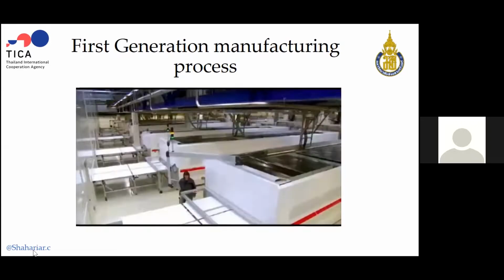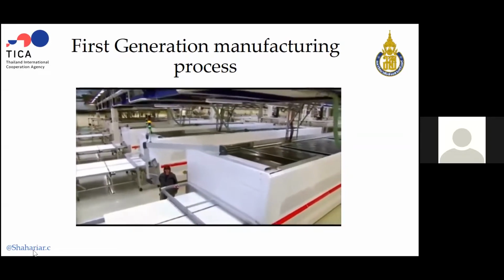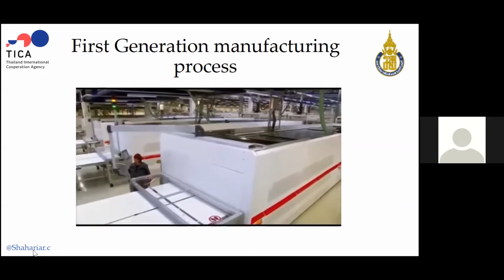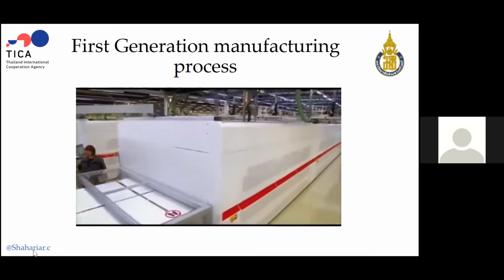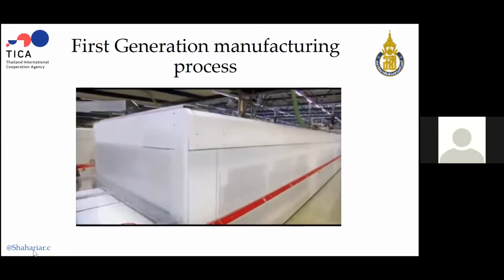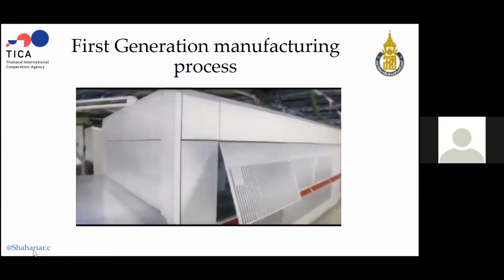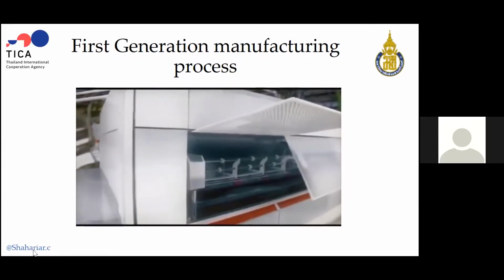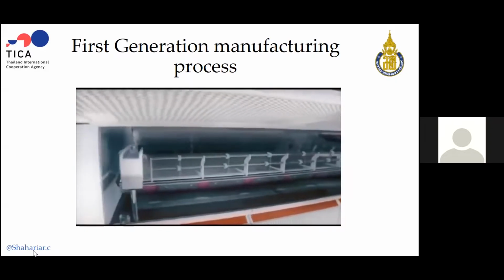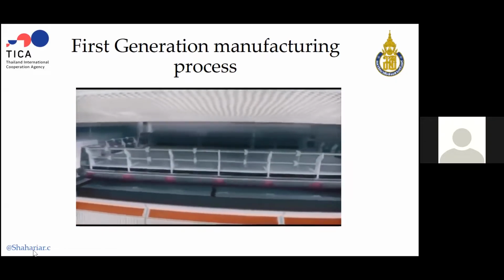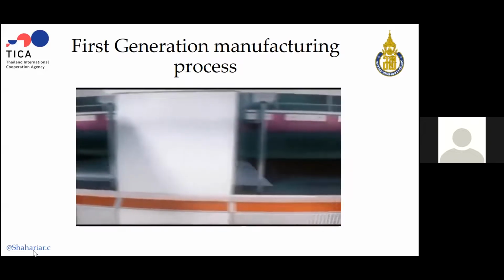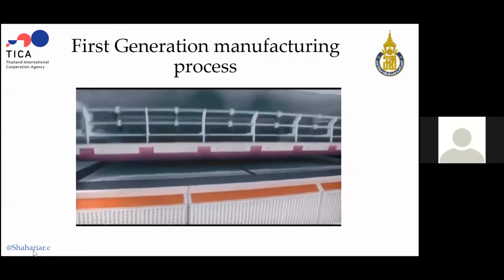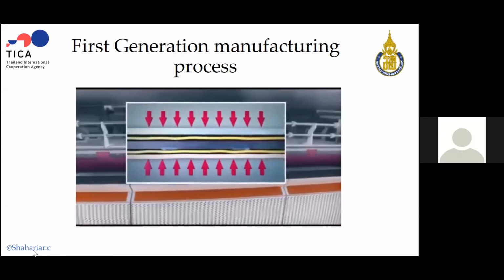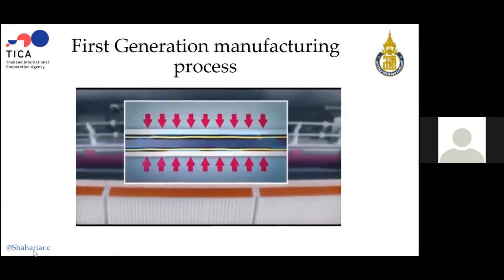Properly sorted into groups of four, the modules are now laminated. A look inside the laminator reveals exactly how this works. Glass, films, and cells are warmed in a first chamber to approximately 150 degrees Celsius. In the second chamber, the EVA films are melted while the air between the films is removed by a vacuum.